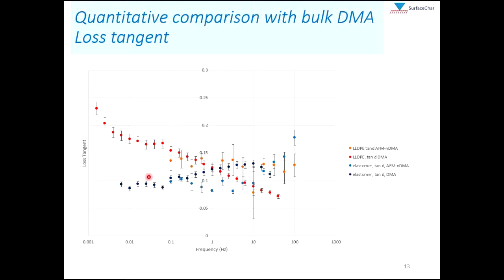We can see in the bulk DMA, we actually get a crossover for these loss tangents at a low frequency, at about 1 hertz. At the AFM-nDMA, we also see a crossover. It comes at a little bit higher frequency, a little bit above 10 hertz. So we can see a little bit of discrepancy between the AFM-nDMA and the bulk DMA, but in terms of the absolute values, nice accuracy between our AFM-nDMA and the bulk values.